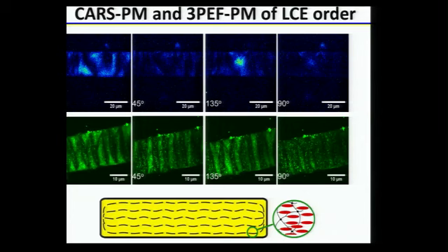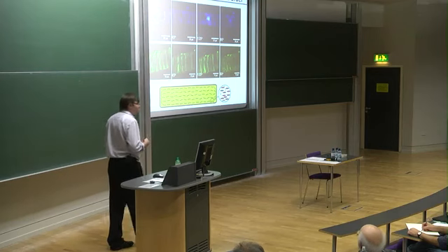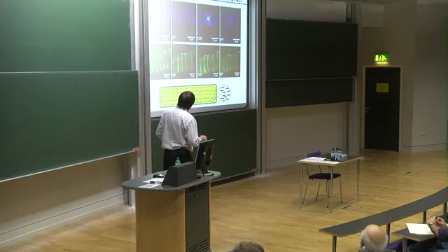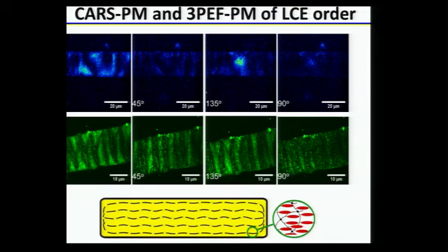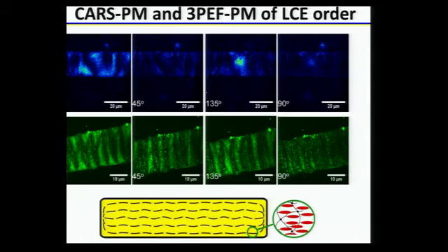And so in those particles that I demonstrated, we have the director field on average along the cylinder, which was obtained by means of applying a strong magnetic field during the time of photopolymerization. And we can see by means of multiphoton fluorescence imaging with different polarization states, as well as CARS microscopy, that inside of this particle we have a weakly undulating director field, as depicted in here. You can also notice tiny little dots. Those indicate the photoluminescence coming from tiny nanoparticles that we deliberately introduced into such a medium.